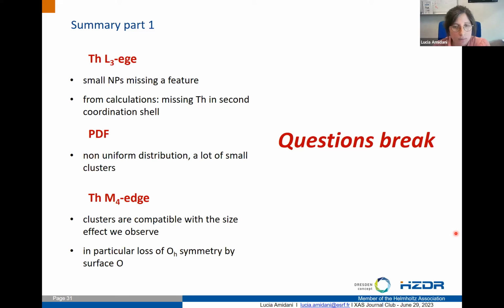So to me, ideally, we should measure the L3 edge on a cluster to see what is really the effect. And to trust what I see in my calculation for the white line, I would like to have a more realistic structure of my nanoparticles, because I think this part is more sensitive. So it is an open question. How big the effect on the white line is for surface atoms, I would need to measure a cluster to really clarify. And this I don't have. Thank you.